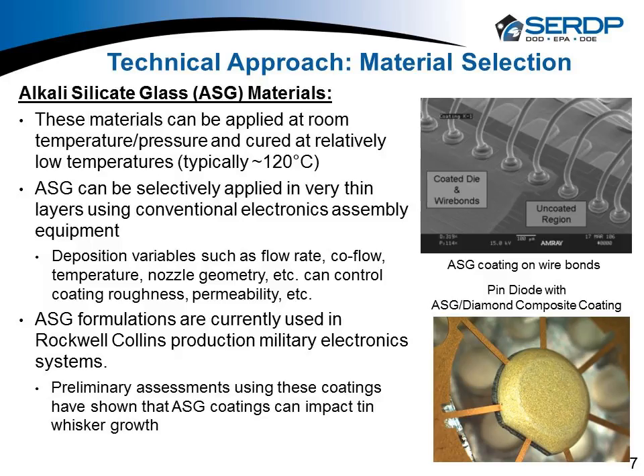If we go to slide 7, a little bit on liquid glass or alkali silicate glass, ASG specifically, a very nice material. We've been using them for a couple other products, but you can control the deposition rates. They're highly tailorable to what you want to do. They also cure, and when I say cure, these are coatings that are based on a water solution, not solvent solutions, so you're driving off the water. But it happens at right around 120, 125 degrees C, and those are temperatures we see in the factory every day in terms of curing other types of adhesive materials, so that wasn't a shock to the system.